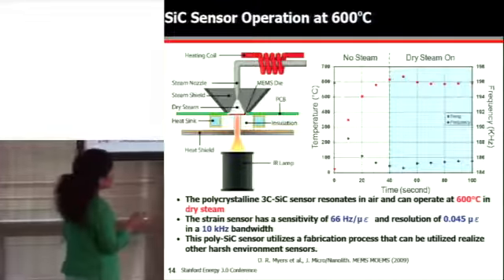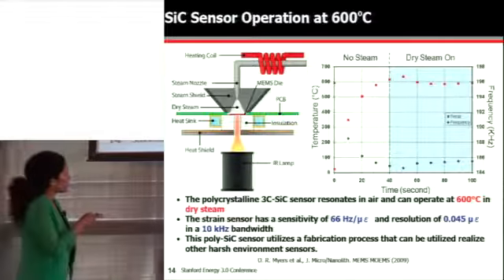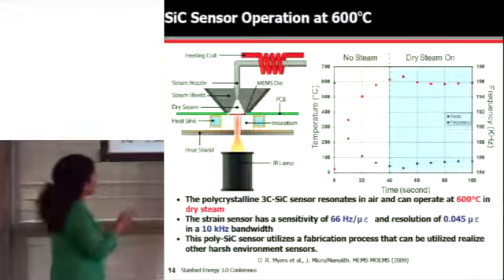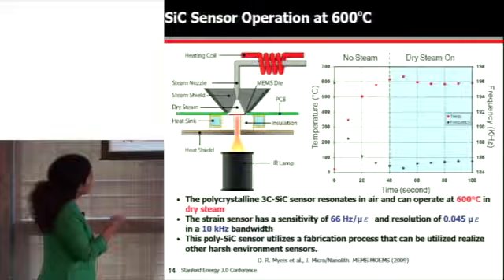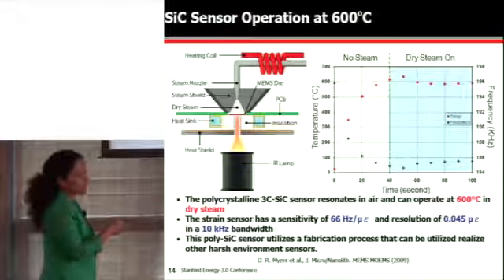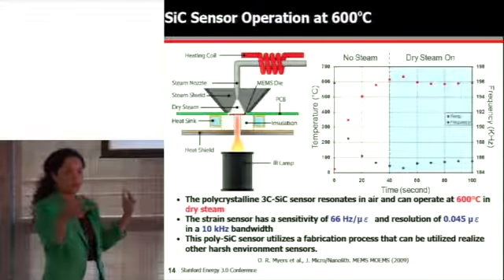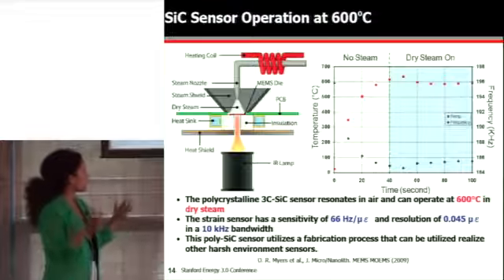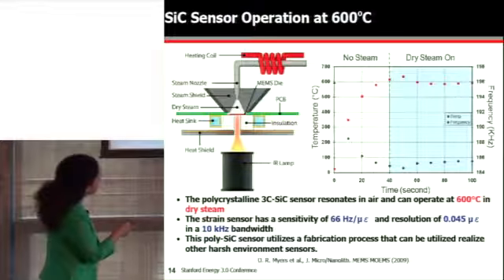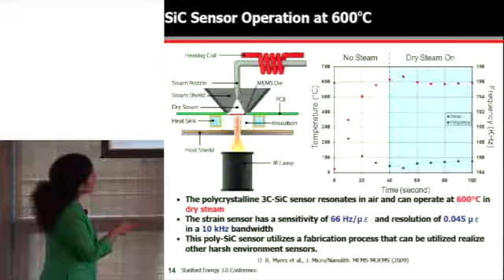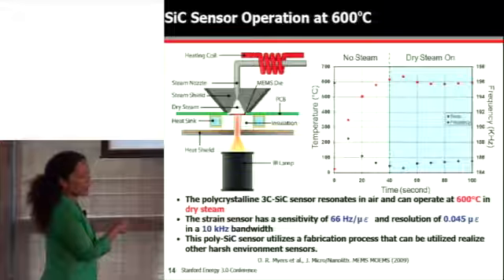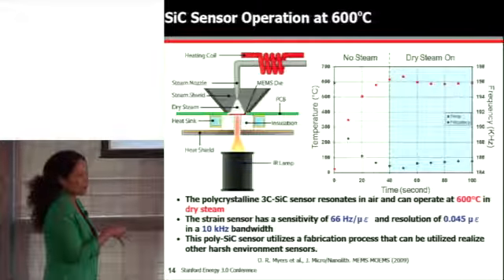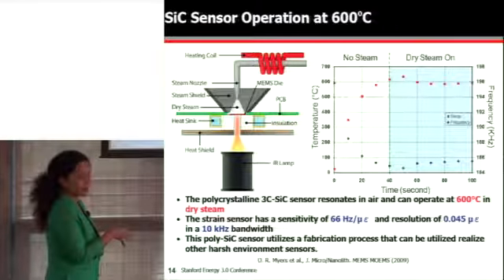This is the temperature ramp going from room temperature up to 600 degrees Celsius. The blue dots here are showing the frequency at which that device is vibrating. Remember those electrostatic interdigitated comb fingers, those are vibrating. As we get to 600 degrees C, you can see that the device continues to operate. We're still exhibiting frequency change in the device. So this is a functioning silicon carbide sensor at 600 degrees Celsius.